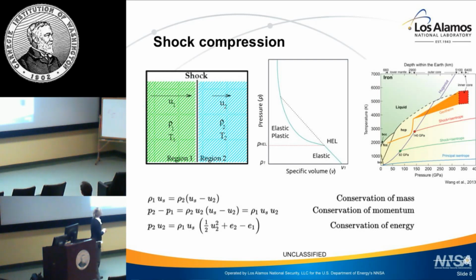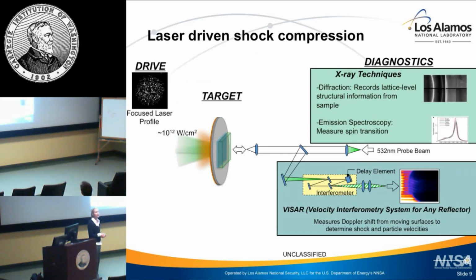The new component here is that we're going to utilize X-rays in a new way. High fidelity temporal resolution is going to be the key. We can collect diffraction, but I'll also mention some X-ray emission spectroscopy, bringing into play new X-ray spectroscopy techniques that can be combined with shock compression. We also have the standard workhorse, a velocimetry technique, measured in tandem with our newer X-ray diagnostics to benchmark shock speed and particle speed of our material.